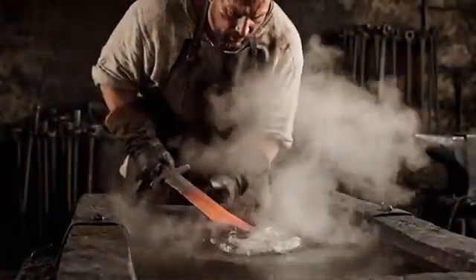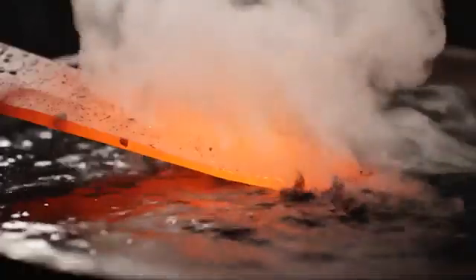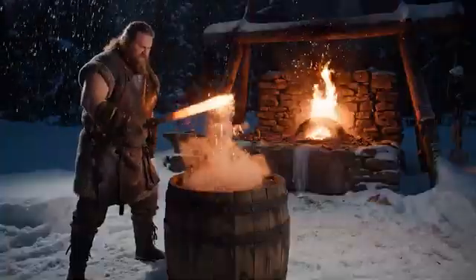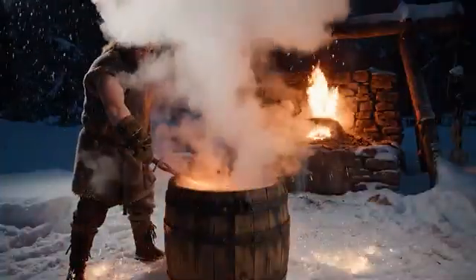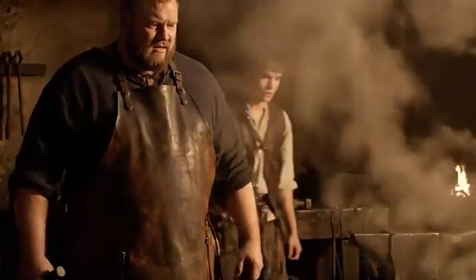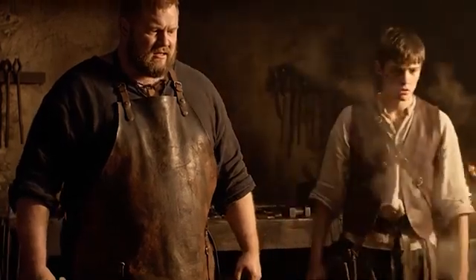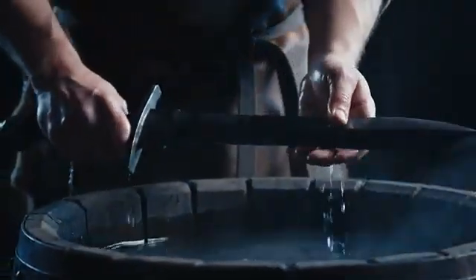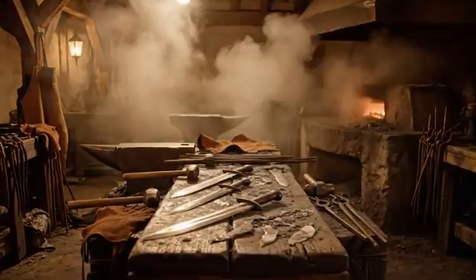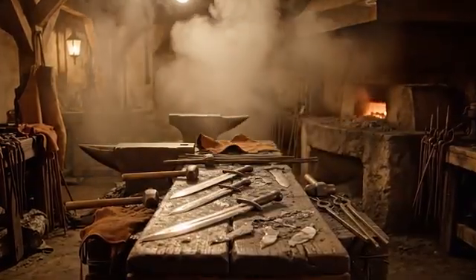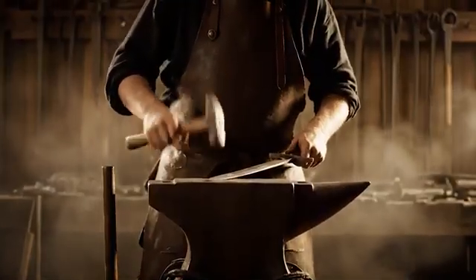This moment was pure magic and a lottery. If the blade was heated unevenly or had internal defects, it could crack or warp right in the middle of the hardening process. Historians believe that the percentage of rejects at this stage was very high, even for experienced craftsmen. After hardening, the blade became as hard as glass and just as brittle. If someone tried to strike with it, it would most likely shatter into pieces.